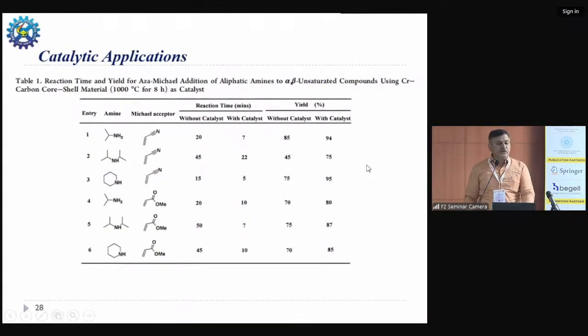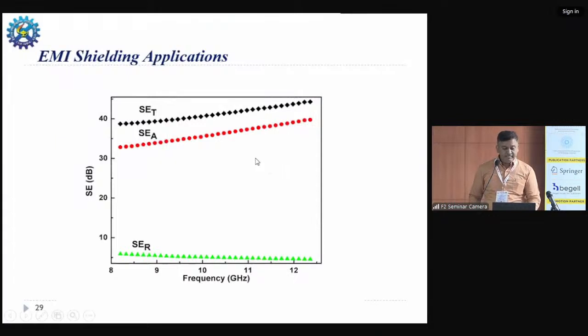And we tried to use this for two applications. One for organic reaction catalysis, where we tried an aza-Michael addition reaction, and we used this material as a catalyst, and we found increased yield with reduced time for the reactions. And we also used this for EMI shielding applications, and we show very good shielding efficiency for these materials, where in the total shielding efficiency, the absorption coefficient is more compared to the reflection.